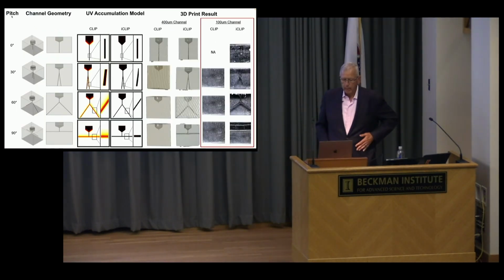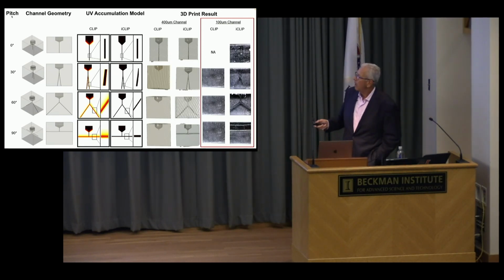So this is work by Ian. And now you see a vertical channel. You don't have overcure issues on a vertical channel because light's always going vertical. But as soon as you start making a channel that deflects in an angle, when you start having the light come out, you have increasing difficulty to print the channel to the point where this horizontal channel will overcure. Well, we compare CLIP versus iCLIP, and you see we can't resolve the channels with CLIP. But when we're pushing resin through the channels, we can.